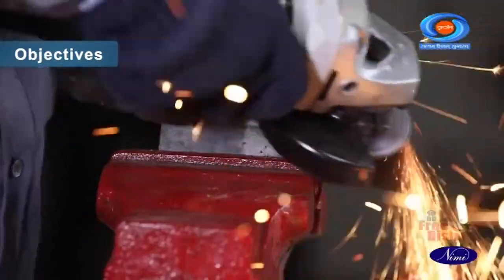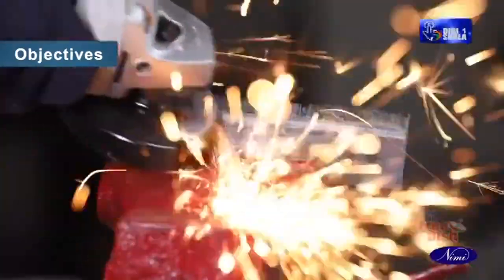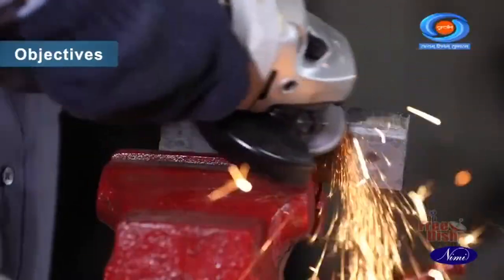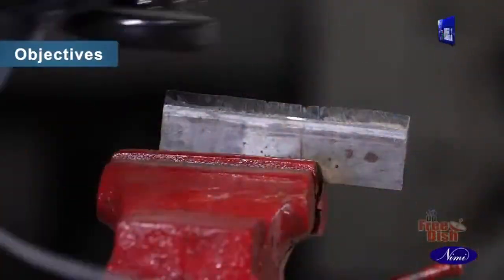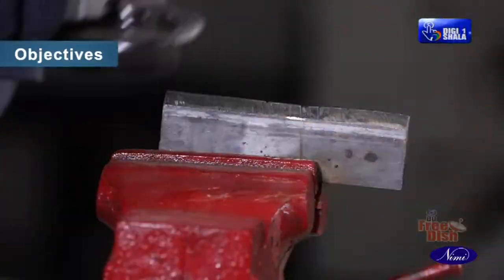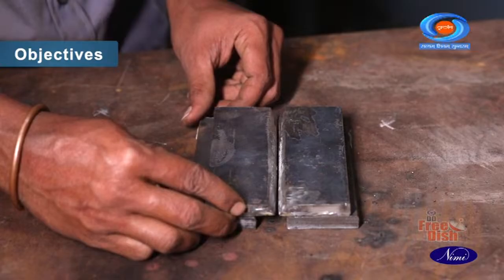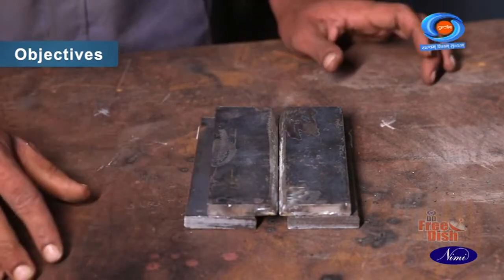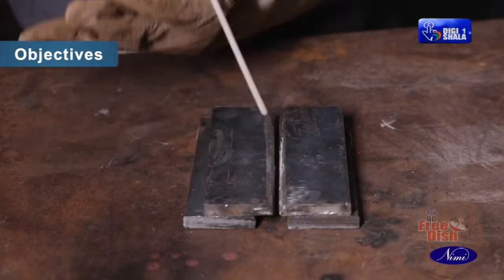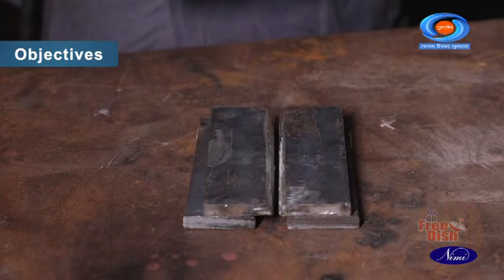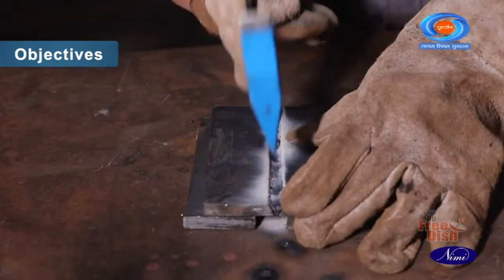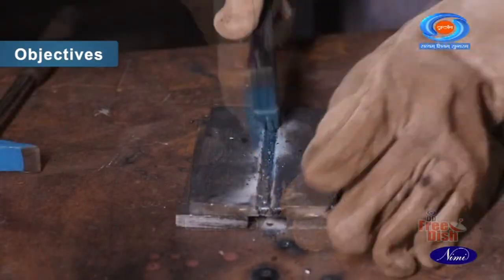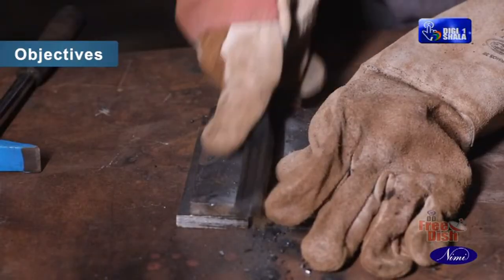Grind the bevel edges with proper root face for single V butt joint. Set the plates with a root gap of 2 mm and proper distortion allowance. Deposit root run in single V butt joint to ensure complete penetration. Deposit intermediate and final covering runs to obtain proper fusion and reinforcement. You will also be able to inspect the groove weld for surface defects and uniform root penetration.